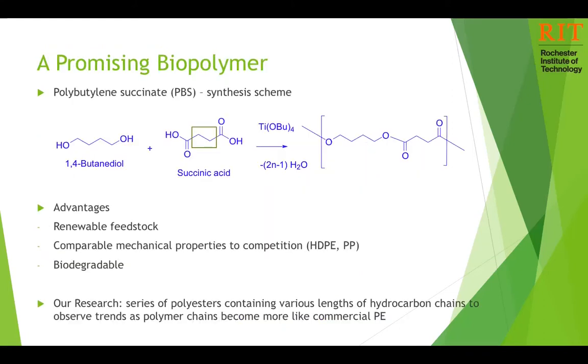Polybutylene succinate, otherwise known as PBS, has become a promising biopolymer in recent years. It is semi-crystalline, thermoplastic, and synthesized through a polycondensation reaction between 1,4-butanediol and succinic acid, as shown in the synthesis scheme above. PBS has such a great potential because both its reactants can be produced via a sugar fermentation reaction instead of using the traditional petroleum-based feedstock. Its mechanical properties are also comparable to commercially used polymers such as high-density polyethylene and polypropylene. However, PBS is considerably more degradable than those.